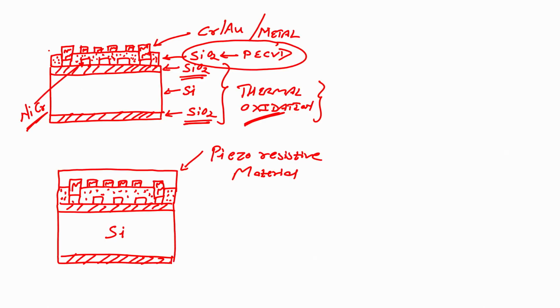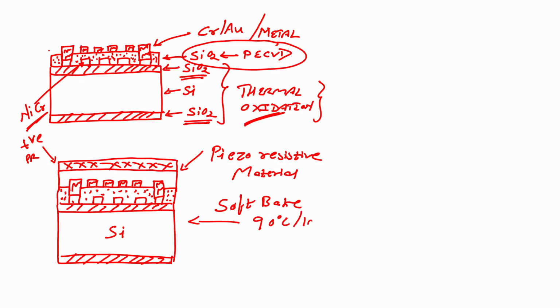Once you do that, what you have to do? You have to perform lithography, and all of you know how to perform lithography. We will spin coat positive photoresist, right. Let me put checks for positive photoresist. What after that? What is the step after positive photoresist? I will soft bake the wafer at 90 degree centigrade for 1 minute. All right. And after soft bake, next step is to load the mask, and we only want the material which is a piezoresistive material to be on the interdigital electrodes and not on the contact region, right. Is it correct mask? No.